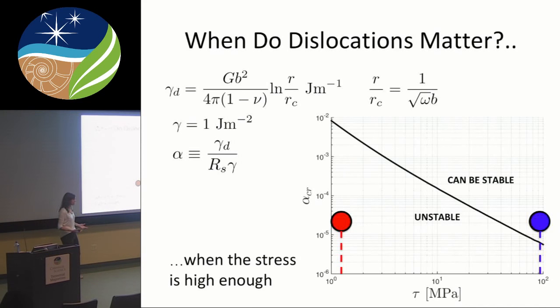So say for a low stress of about 1 megapascal, still somewhat typical stress within the lithosphere, my critical alpha is way high. The alpha I should actually be observing in an olivine-like material at this stress is way lower. So at these conditions, dislocation dynamics that I was talking about just now probably don't matter very much. It only starts to matter when the stresses are relatively high. So at high stress, dislocation dynamics are more important, and energy associated with the dislocations is relatively higher. And so the critical alpha would be way lower.